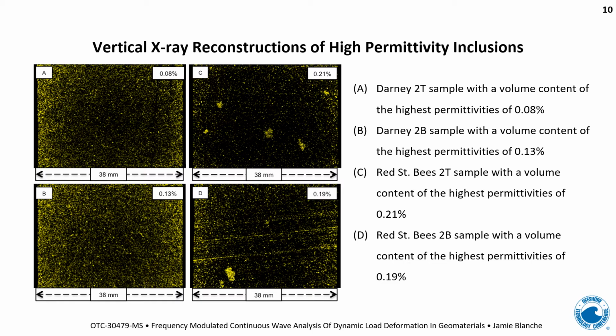The left-hand images, top and bottom, the Darney Sandstone, show a fairly uniform distribution of high permittivity inclusions, metals such as iron, aluminium content in the clays and feldspars. The right-hand side images show the Red St sandstone, which exhibits concentrations of high permittivity inclusions and layering. So what we ascertained from this characterization work was that the Darney 2T sample has a volume content of the highest permittivities of 0.08%. The highest content permittivities, as I say, are distributed metals.